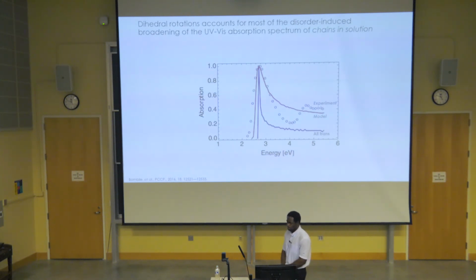When you showed the dihedral potential of the P3HT in chloroform, I noticed there was a really sharp peak right at 180 degrees. What's that all about? I'm not entirely sure. It turns out that in our simulation the chains didn't stay much in exactly that position.